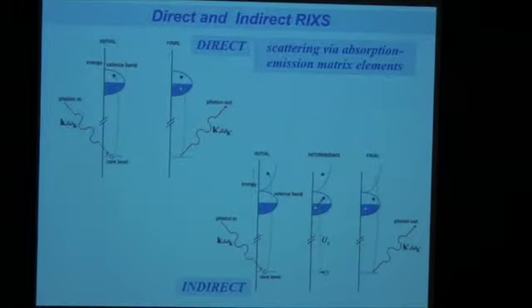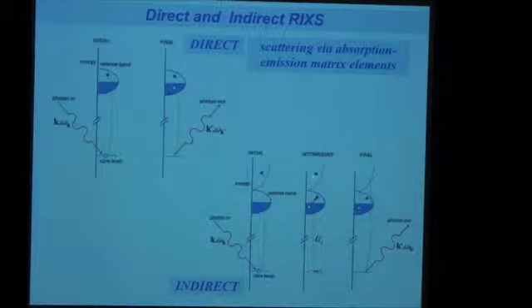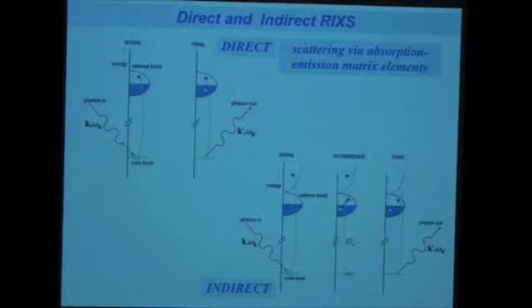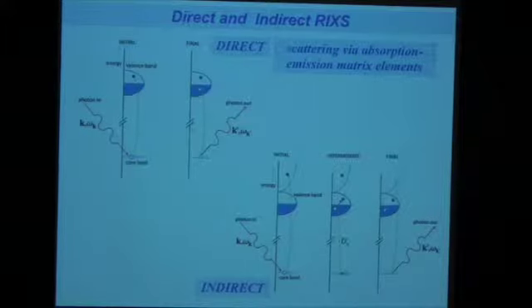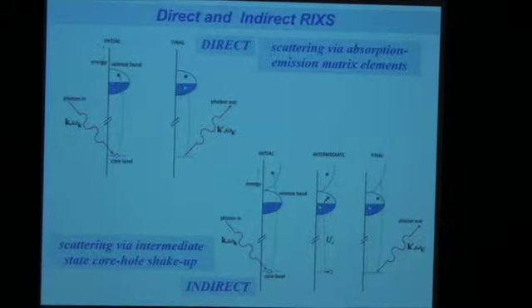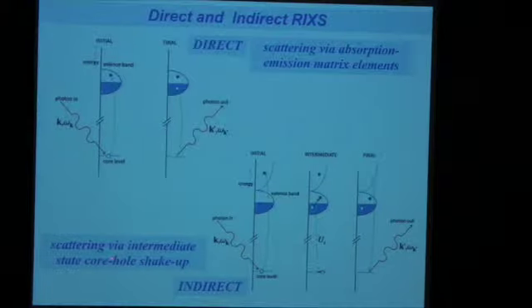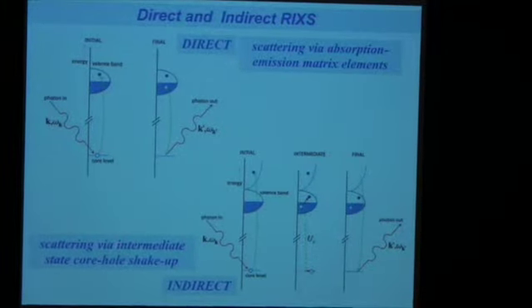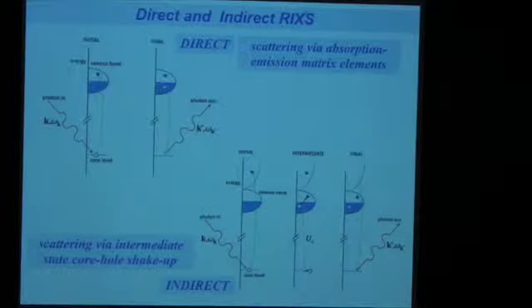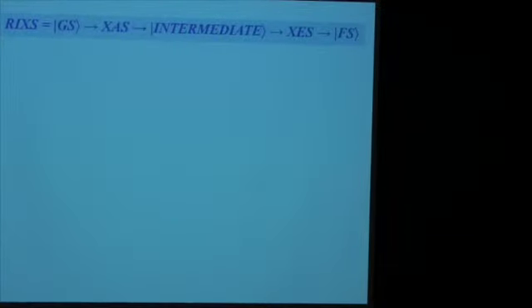And after this core hole interaction, this electron that was just a spectator decays again, and the photon is emitted, leaving behind this electron-hole excitation. So in this case, the inelastic scattering occurs via the intermediate state core hole shakeup. That's one way of calling it. Okay. So now you would say, well, that sounds a bit complicated. And actually, that's what kept many people off from theoretically considering RIXS, and also the experimentalists, except the Swiss ones, from starting to do these experiments.